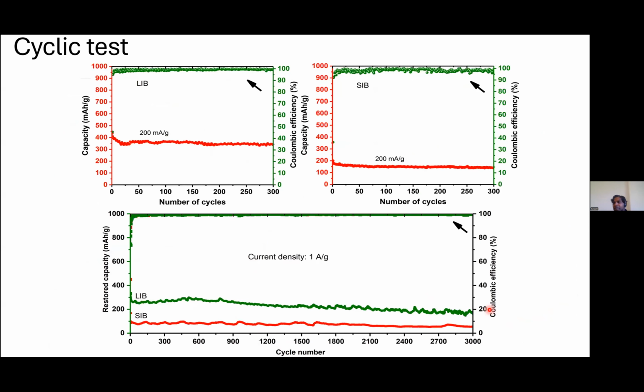And the next one, cyclic test. How long can this cycle go? So in two different current densities, we have tested for both. One with a smaller current density, 200 milliampere per gram, almost always, for all the materials I do in our laboratory. One smaller current density, one higher current density, so that we can compare at a particular stage what material behaved how. For these ones, lithium ion battery and sodium ion battery in a smaller current density, absolute consistency is quite good, up to 300 cycles.